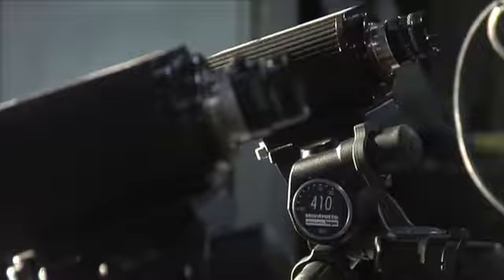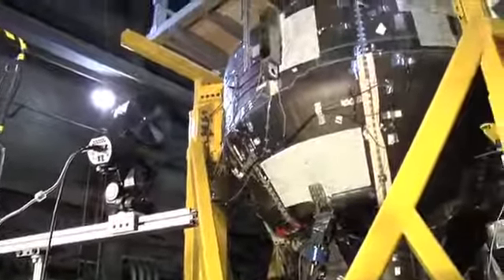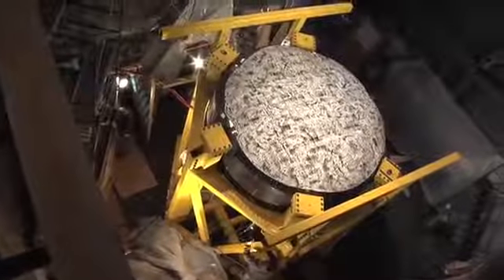The tools we use range from a tensile testing machine pulling on coupons to get their strength and specific stiffness, to some pretty high-tech imaging methods to get full field strain of a complex article, to look at failure modes where things start to break apart. Other times we'll do chemical analysis to figure out whether a process has developed like we expect. Like the cure of a composite resin, you can evaluate it chemically to see how far it's progressed. And that's often important to make sure that you control processes at the coupon and full-scale level.